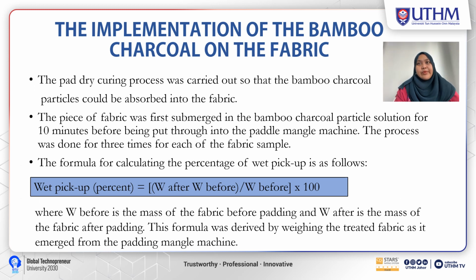Next, it will be the implementation of the bamboo charcoal on the fabric. Okay, the pad dry curing process was carried out so that the bamboo charcoal particles could be absorbed into the fabric. The piece of fabric was first submerged in the bamboo charcoal particle solution for 10 minutes before being put through the padder mangle machine. The process was done 3 times for each of the fabric samples.